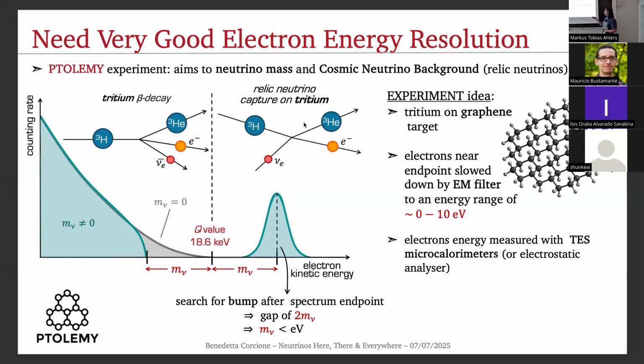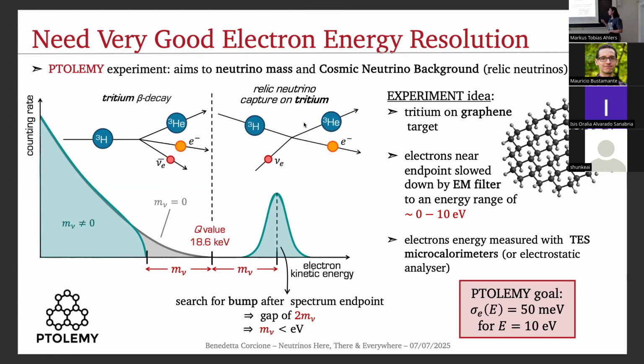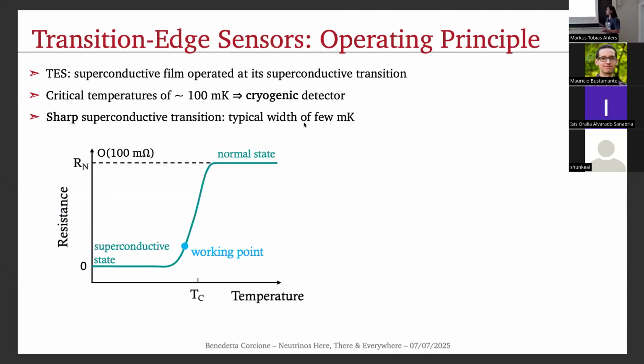And the Ptolemy goal in terms of energy resolution to hope to see such tiny modifications in the spectrum is 50 milli-electron volts on electrons at 10 eV. So now that the framework is clear, I hope, we can talk about transition edge sensors and electrons to perform these measurements. So transition edge sensors are superconductive calorimeters, and superconductivity exploits the strong dependence of resistance upon temperature.